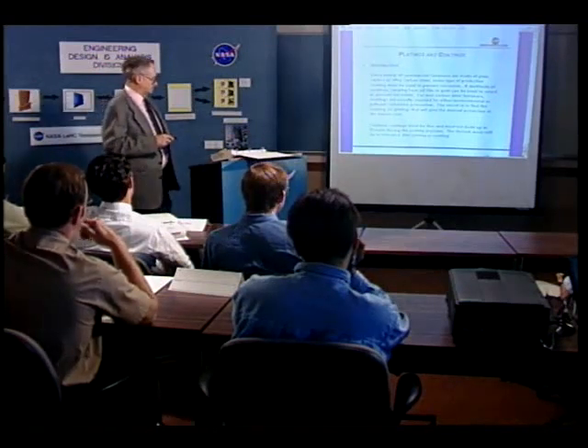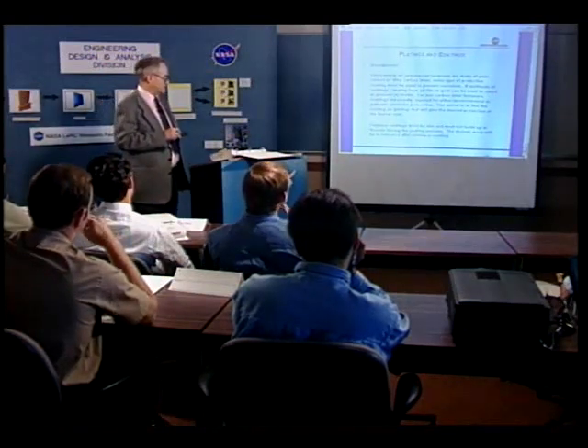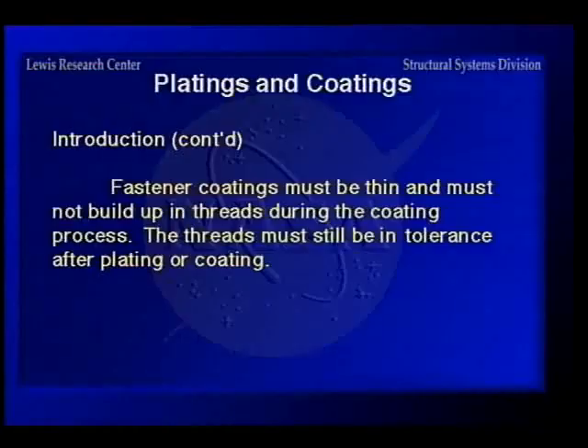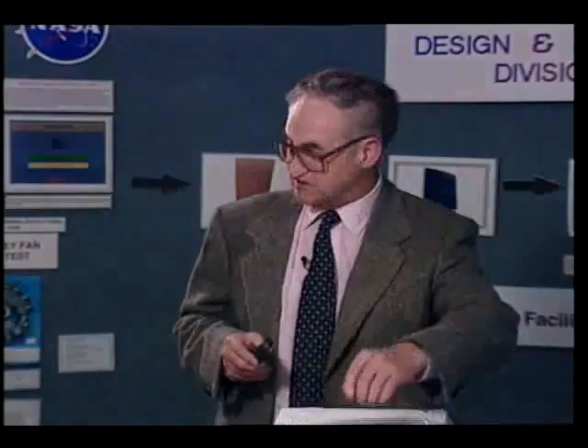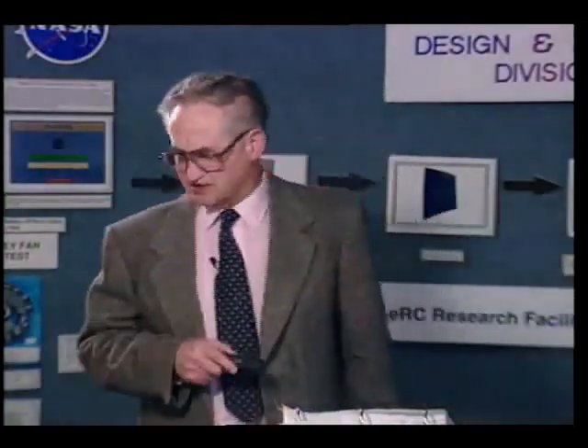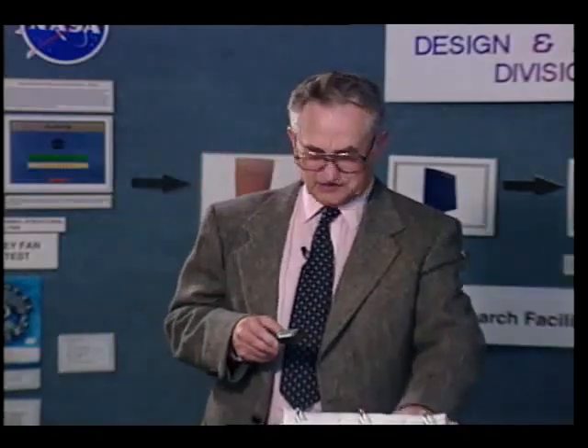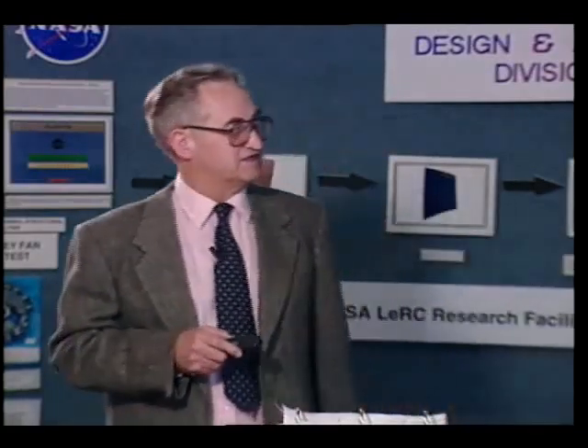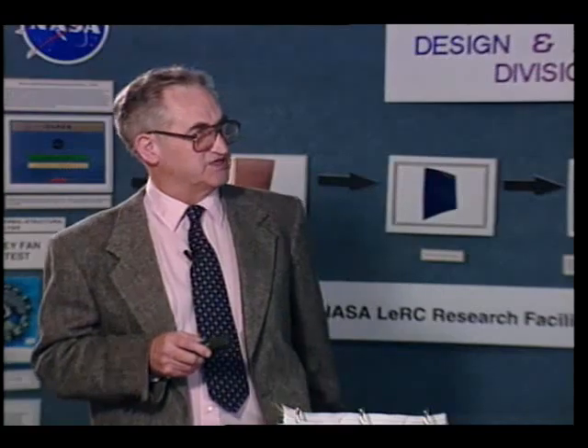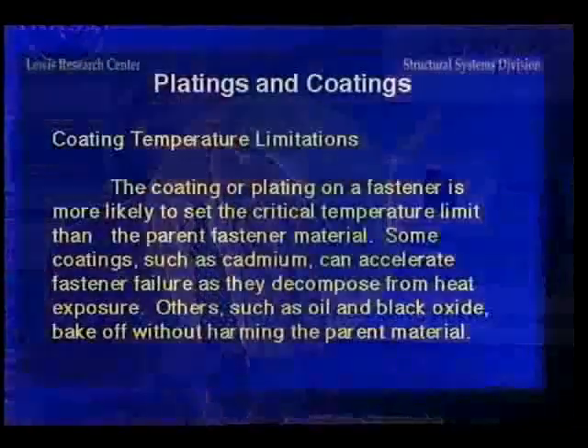So the other thing is with fasteners, you've got to have a thin coating because the fastener threads have to be within tolerance after the coating, which is important. Now, I know that if you get nails or something like that, Ron Romanchuk drives nails all the time that have been galvanized, and that's a dipping process, but it's not used normally on threaded fasteners.